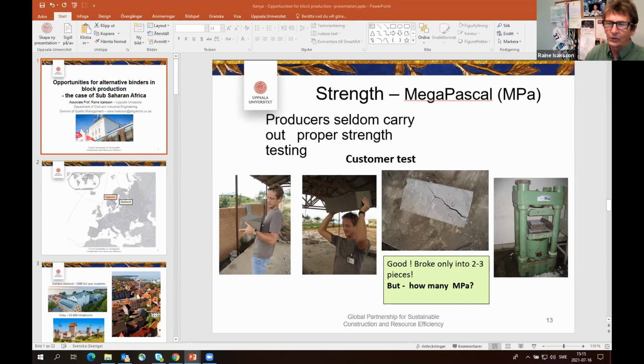then you know this is not good. But I think at that level, you are probably down to 0.5 or 1 megapascals. As soon as it's more than 1 megapascal, it passes this simple test, but the customer doesn't know if it's 2 or 8 megapascals. It's almost impossible to know when pressing with your fingers and testing. So measurement is a big problem. How can you improve when you cannot measure?